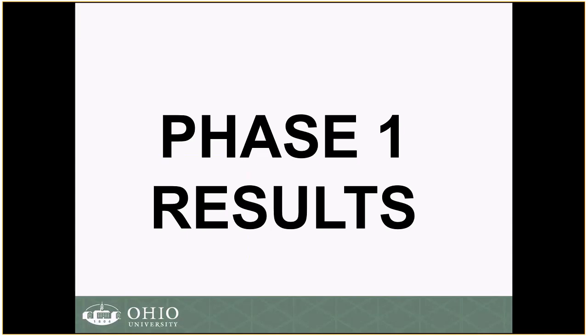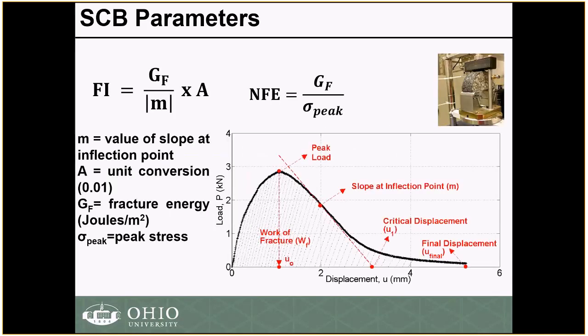So, starting with the phase 1 results. For the SCB parameters, we looked into 2 parameters. The first parameter, which is commonly used, is the flexibility index. I'm showing the definition of that flexibility index. It depends on the area under the load displacement curve, as well as the slope of the post-peak curve, which is shown here.